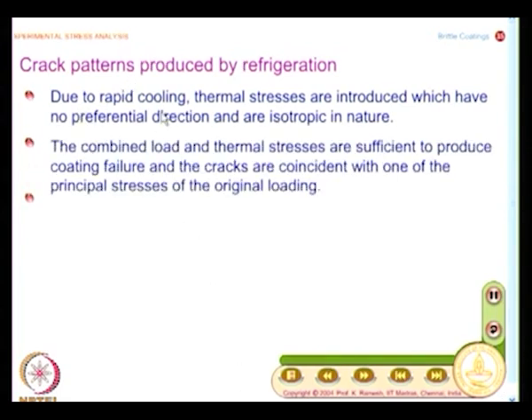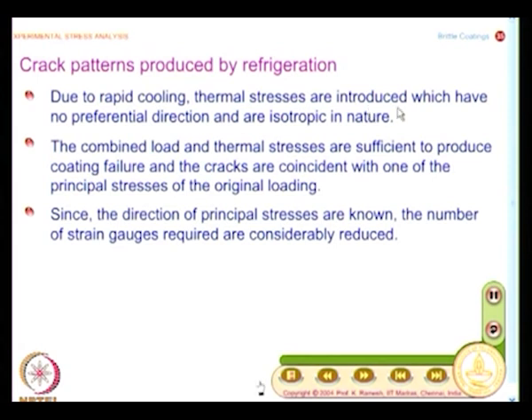Due to rapid cooling, thermal stresses are introduced which have no preferential direction and are isotropic in nature, and what you have is the combined load and thermal stresses are sufficient to produce coating failure. So, you are able to reveal crack patterns in regions which have not appeared earlier, and this approach is known as crack patterns produced by refrigeration. And once you have got the cracks, the directions of principal stresses are known, and I can reduce the number of strain gauge channels. So, it is a very simple extension of basic methodology of brittle coating.